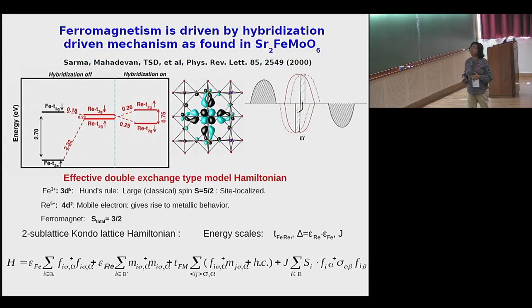Now, what makes it a ferromagnet? This is a hybridization driven mechanism, which was first discussed in the context of Sr2FeMoO6. The idea is the following: you have a large core spin sitting at the iron site, which is highly spin split, and the negligibly spin split rhenium t2g states fall within the spin split states of the iron. Now you switch on the hybridization between the iron and rhenium, which pushes the rhenium t2g states upward in one spin channel and downward in the other, therefore setting up a renormalized spin splitting on the otherwise non-magnetic rhenium site, which is oppositely oriented to that of the iron. And since all of the iron spins have to be oppositely oriented to the induced rhenium spin, the iron spins in the iron sublattice become parallelly aligned, driving the ferromagnetism.